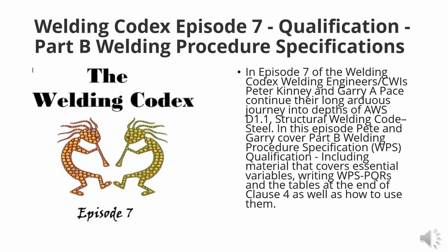The other one that does exist is all-weld metal, which, I was going to say, exists but is not common. And then macros, and basically we use macros for PJPs and fillets. The other test that's commonly done is the macro etch test, and that's primarily just for PJP groove welds to determine weld size, and for fillet welds. That's pretty much where you'll see macro etch tests done in this spec. There is also an all-weld metal tension specimen, which is basically taken out of the center of a groove weld. It is not that common in the D1.1 world to pull those. So those are some things that you might see, but not very often.